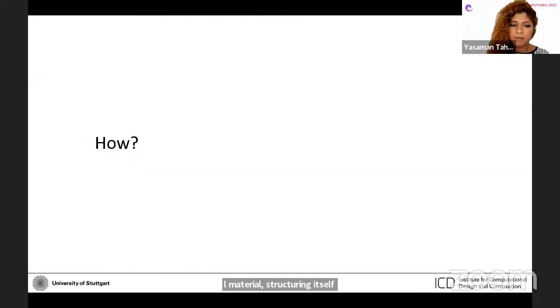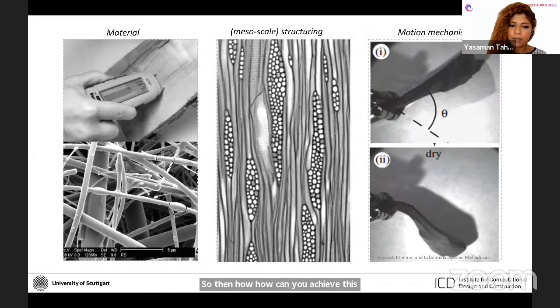So then how can we achieve this? We can look at nature, for example, the pine cone again. The way that the pine cone can achieve the shape changing capability is through taking advantage of both inherent material properties and the material structuring in different hierarchical length scales. So on a micro scale level, the hygroscopic microfibrils are extremely hygroscopic, meaning that they can swell when they absorb water or moisture from the air. And then through specific arrangement of these cellulosic microfibrils within the plant structures, the swelling can be translated into shape change in the form of bending.